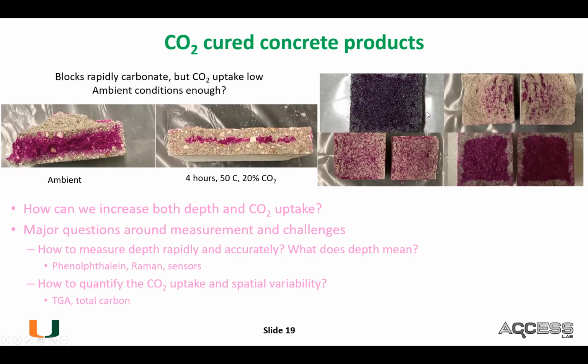Well, maybe not. That test is basically a phenolphthalein dye test, and essentially it's a pH indicator. So if the white portion shows up, it's basically telling you that the concrete has carbonated, or the pH has dropped, meaning the CO2 has gotten in. That is correct. But the thing is, the amount of CO2 we couldn't even measure. A 1% uptake is a different story, but this was not even detectable how much CO2 it was.